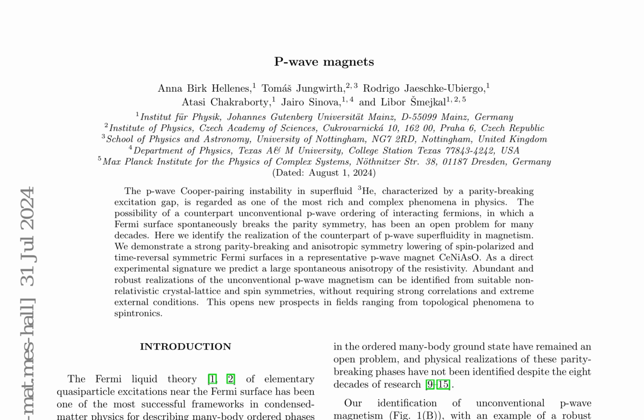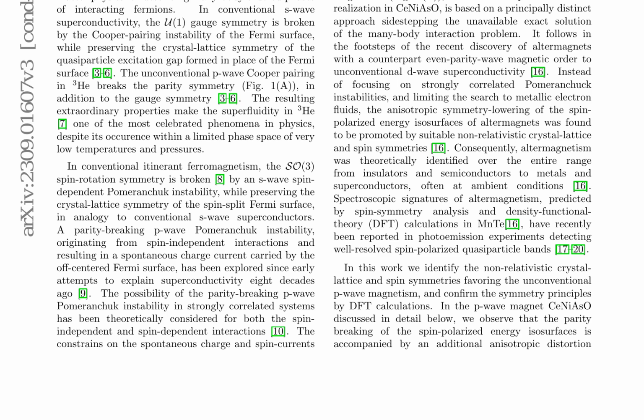This discovery opens new prospects in fields ranging from topological phenomena to spintronics, as it does not require strong correlations or extreme external conditions. In contrast to conventional itinerant ferromagnetism, where the SO(3) spin rotation symmetry is broken, the proposed p-wave magnetism breaks the parity symmetry, leading to a spontaneous anisotropy of the resistivity. This finding is a direct experimental signature of the unconventional p-wave magnetism.